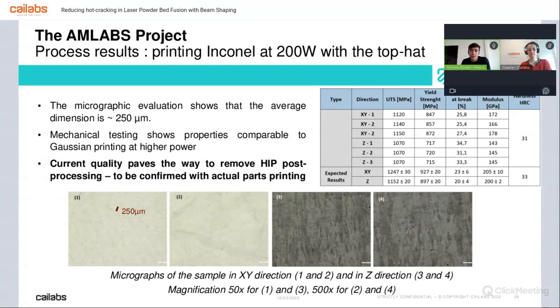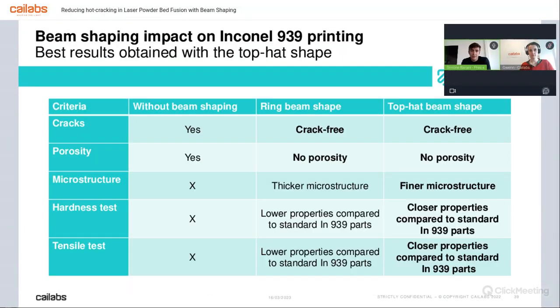Considering that this part is generally heat treated at the end, it's perfectly fine, and it's, as I can say, a very good result, because we have printed. After that, what we have done is printing another job that you will see in the next slide with a small part to see if we have some cracks, and we don't have any cracks. So at the end, the result will be that without beam shaping, we have cracks and we have porosity.